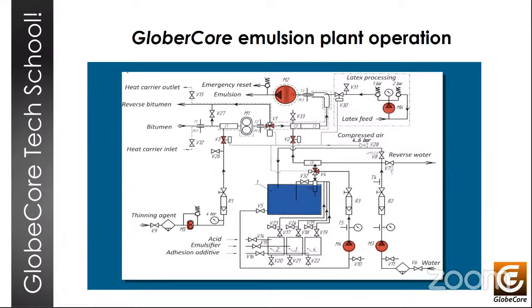And in the C1 mixer, the thinner and bitumen are pre-mixed. And the flow rate of the thinner is controlled by a flow meter R1 and adjusted with the control valve. In the C2 mixer, the bitumen and the water phase are mixed, and the water phase is first pre-mixed with the blend in the C6 mixer. And the percentage of water and blends is controlled by flow meters R2 and R3, and they can be adjusted with the appropriate control valves.